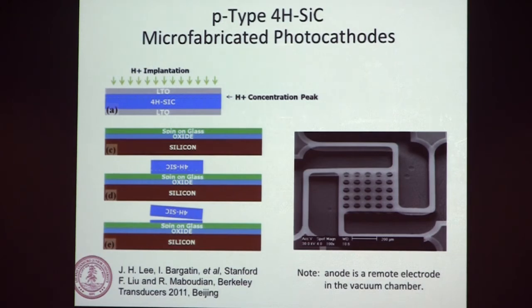So my grad student Jay Lee, and this is at Transducers in Beijing, we have a single crystal silicon carbide from Cree. We do a smart cut process, hydrogen embrittlement, make a wafer with spin-on glass and oxide, flip it over, bond it, and transfer a micron or two of silicon carbide and fabricate one of these structures. We need the crystalline silicon carbide, the P-type silicon carbide, to see this photon enhancement as easily as possible.